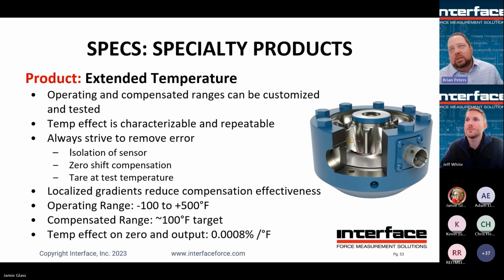If it's a constant temperature test, albeit at an extreme, either cold or hot, you can always get the assembly up to that temperature and then tare the load cell. That's going to remove the zero balance error that was introduced from that temperature change. Now, if it's a changing temperature test, where you're going from low to high or cycling, obviously you couldn't do that, but there are sometimes ways that you can start to remove some of these specification errors from your test measurement.